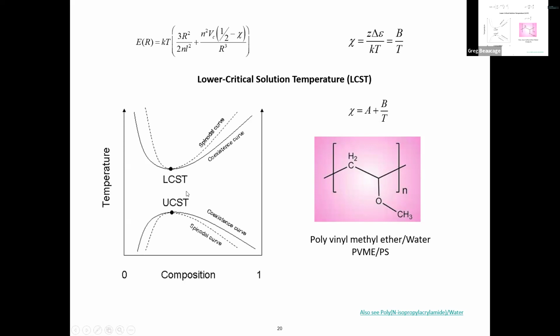You can mix this with polystyrene and it mixes. It's not any two polymers that mix. And also you can mix it with water and it mixes. So it's water soluble, but it's got an LCST. The LCST is right near room temperature. If you hold this stuff in your hand, it'll go cloudy, like white.